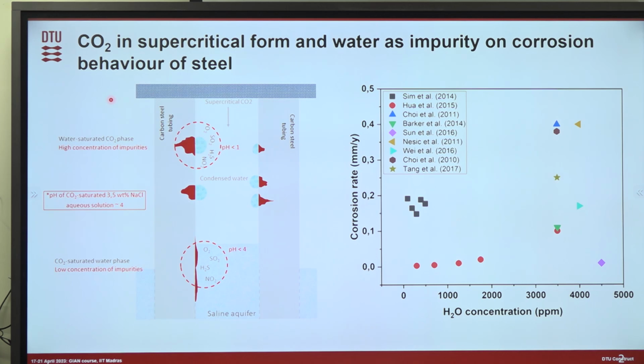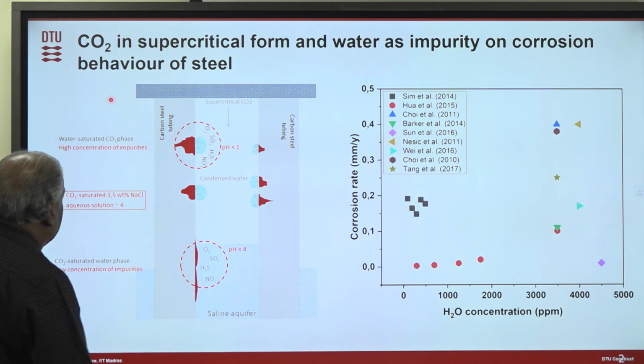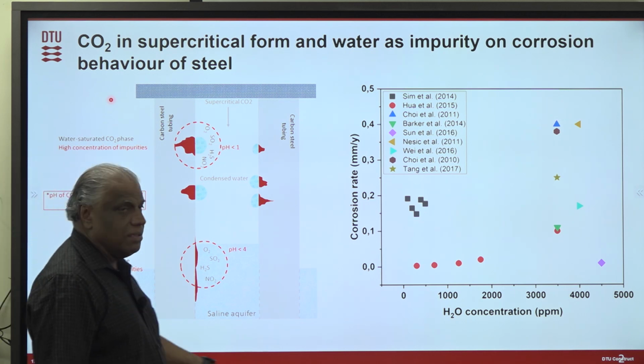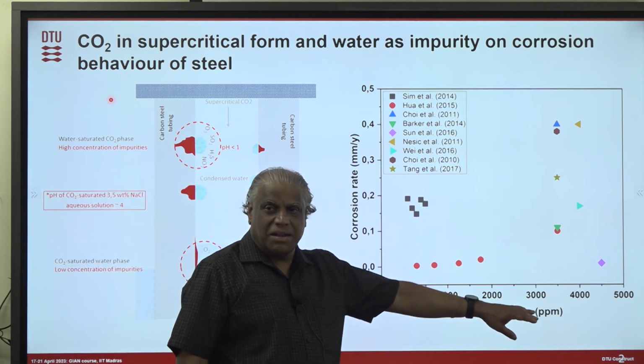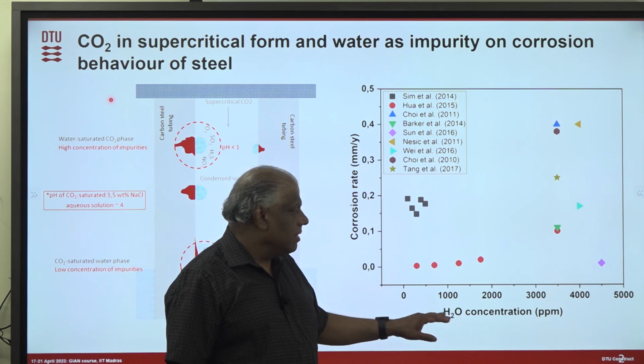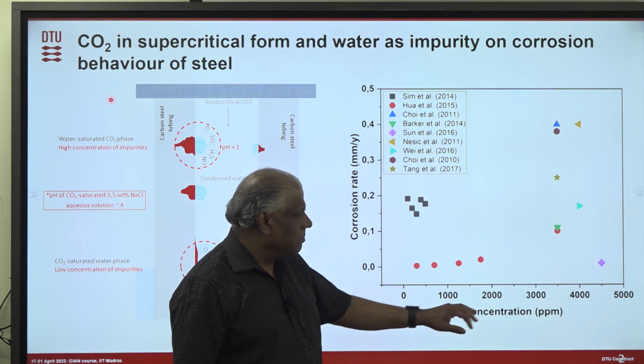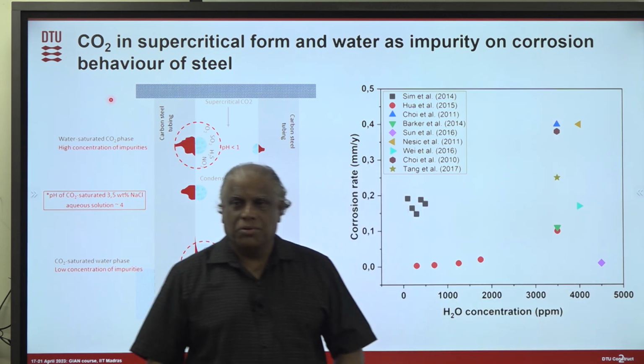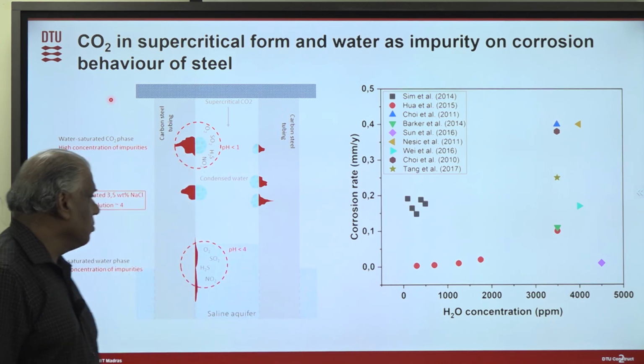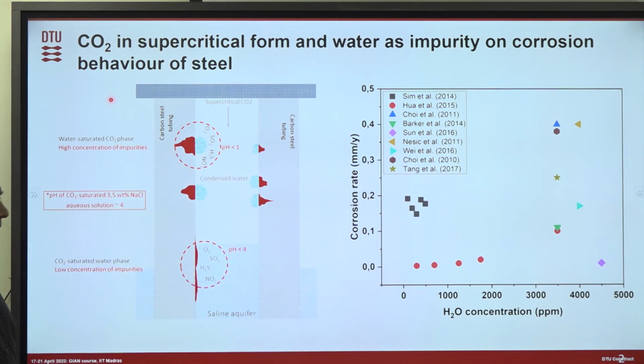So here you can see, for the first case which I mentioned, that you have these CO2 conditions which are contaminated with a very small amount of moisture. You can see that this is 1000 ppm to 5000 ppm moisture content in the CO2. And I mentioned that this is what happens.